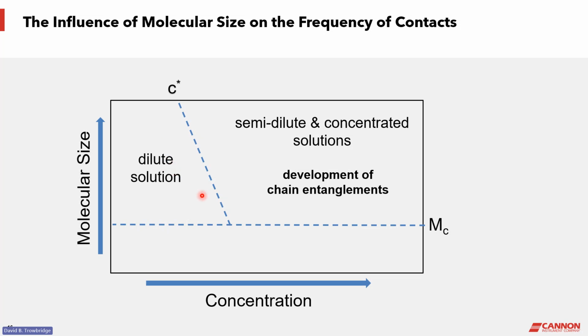Now, the interesting thing about this plot is that this line is at a slope. What that's saying is that at high molecular weights, C star, the onset to semi-dilute, is at a lower concentration because the molecules are bigger. They just cannot fit into the same space at a higher concentration. So the contacts happen at a higher molecular weight at a lower concentration. So that's an important aspect to remember as you're preparing solutions, that with high molecular weight samples, you have to maintain a lower concentration to maintain the dilute solution state. So in the dilute solution, if we maintain no contacts, we have the free mobility of the molecule to deform as required by the dilute solution viscosity theories that we'll be referencing later.